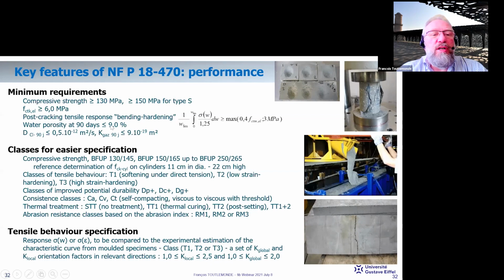Minimum durability properties require water porosity lower than 9%, a chloride diffusion coefficient lower than 0.5 times 10 to the minus 12, and a gas permeability lower than 9 times 10 to the minus 19 square meters.